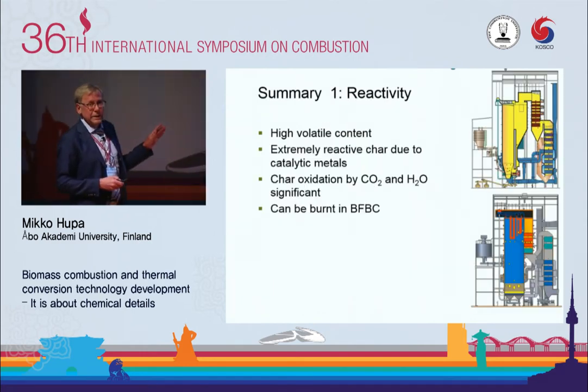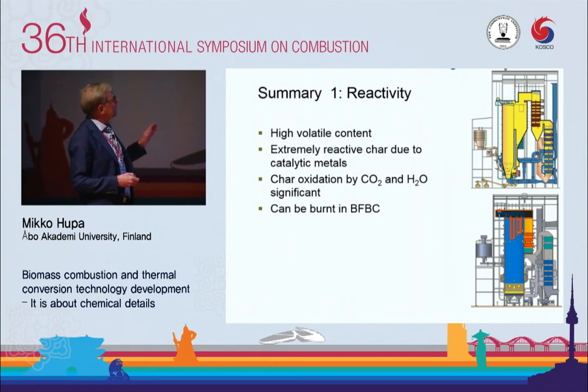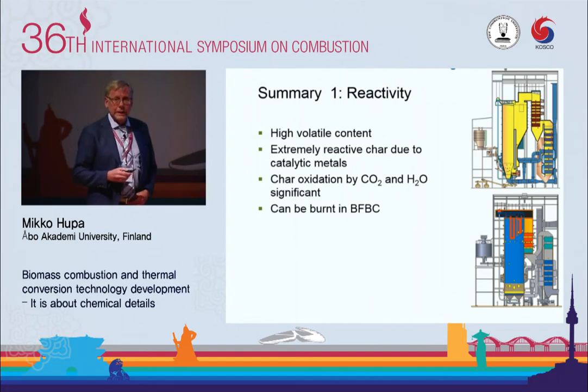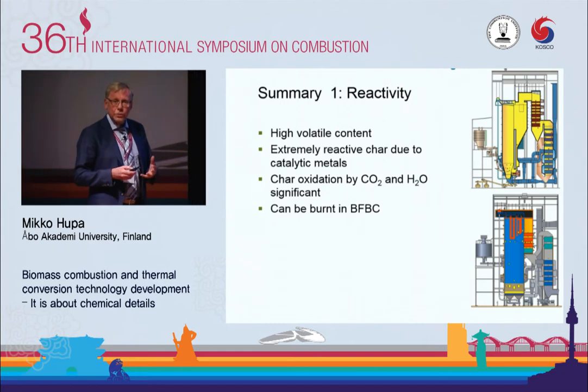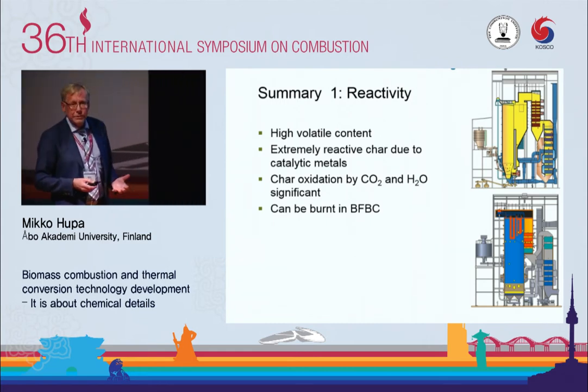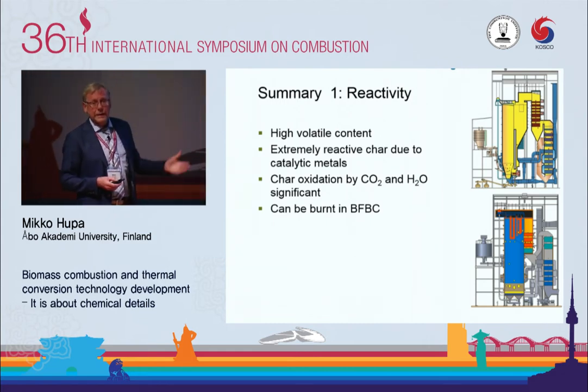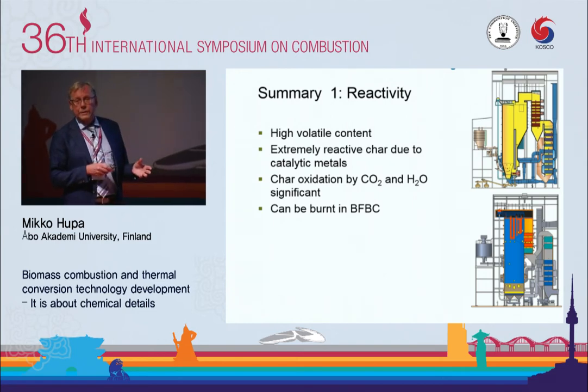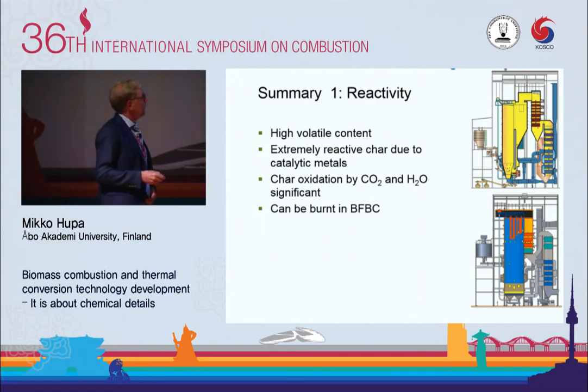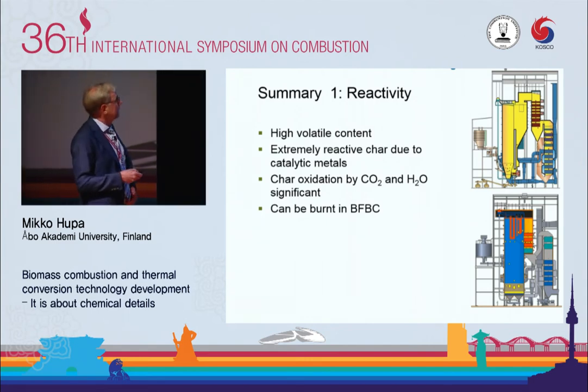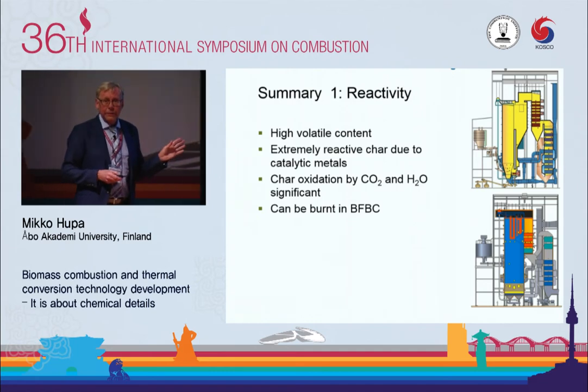The reactivity summary: very high volatile content, extremely reactive char due to catalytic metals. Char oxidation by CO2 and H2O is also so fast that even in ordinary combustion, those reactions need to be taken into account besides the direct reaction with oxygen. So that is, we have seen it when modeling the particle burning, that the gasification reactions need to be taken into account. Otherwise, we don't get it correct. This has a very important technical consequence.